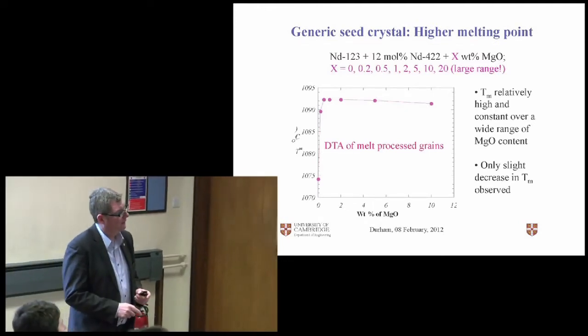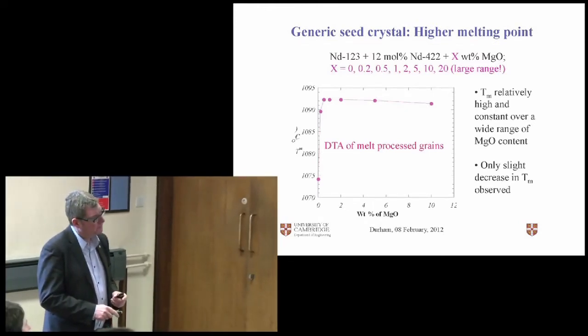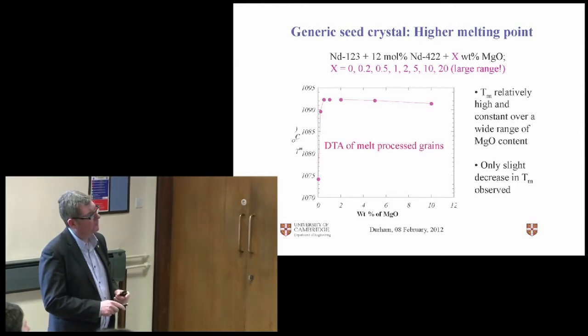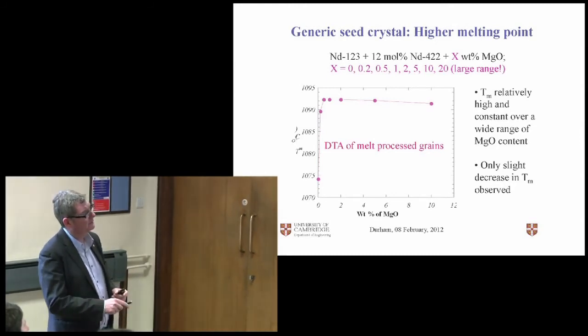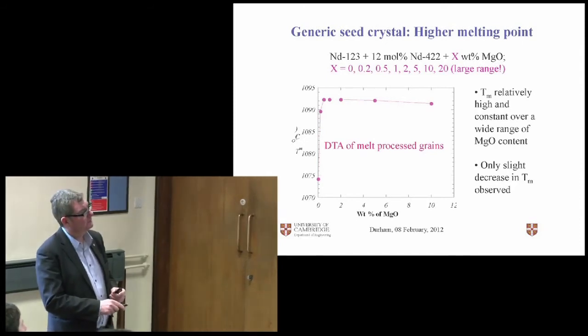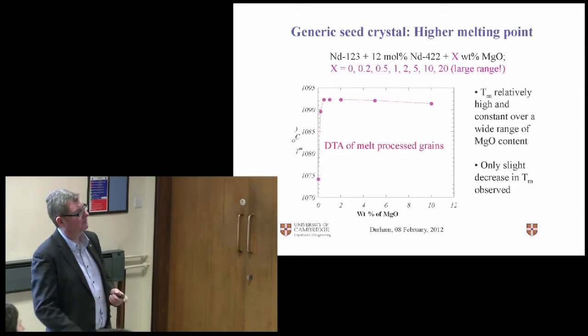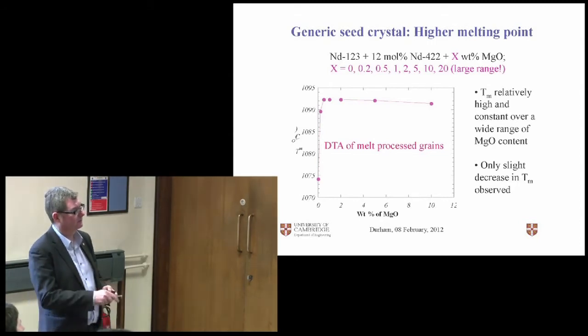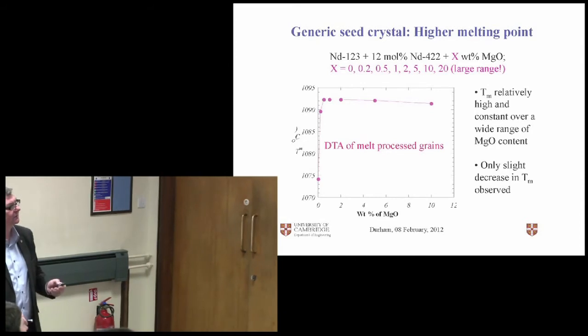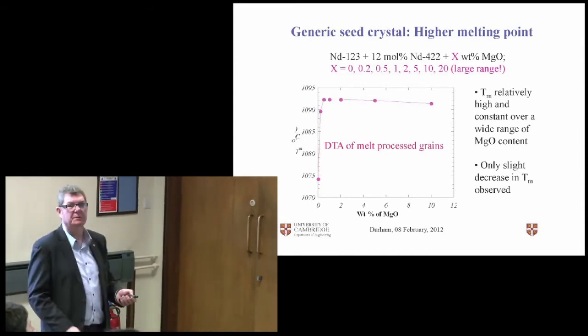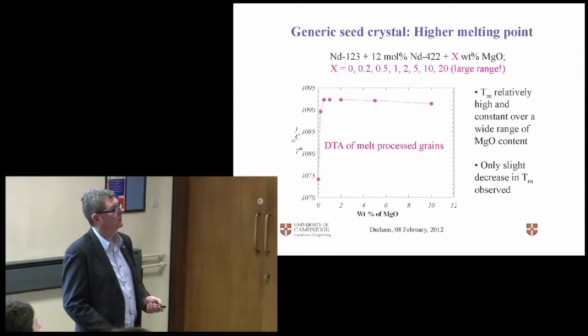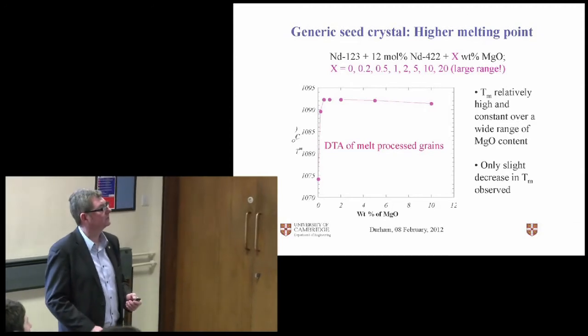If we actually add magnesia, we see that for up to 1 weight%, we get this big increase in decomposition temperature, and then it levels out. So the magnesium is going into the lattice for these small dopants, and here it's existing as a second phase impurity. This was part of Boischi's PhD thesis. So you only need 1 weight% magnesia in neodymium, and you get these very nice seed crystals.